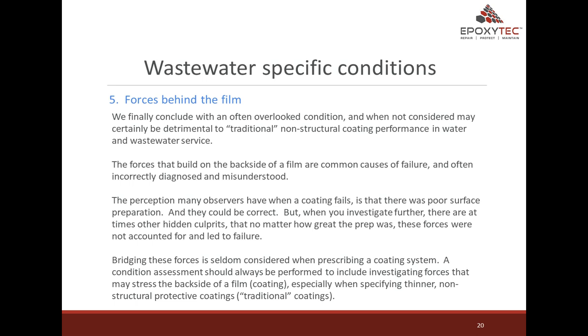And number five, forces behind the film. We finally conclude with the often overlooked condition. And when not considered, it can certainly be detrimental to traditional non-structural coatings' performance in water and wastewater service. The forces that build on the backside of a film are common causes of failure and often incorrectly diagnosed and misunderstood.